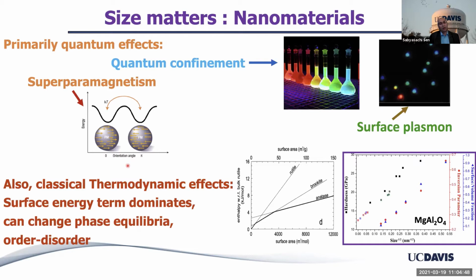But besides these quantum effects, there are also classical thermodynamic effects, which primarily come from the fact that the surface to volume ratio increases a lot when you go to tiny size. It's mostly surface. If you consider a tiny particle, almost 90% of the atoms could be near the surface. So in that sense, the surface energy term dominates and can actually change phase equilibria and change properties of materials. Here are a couple of examples. One is one of Professor Alex Navrotsky's work, who I believe is currently at ASU, when her group from UC Davis did this work. This is the phase equilibria of TiO2 nanoparticles in rutile, brookite, anatase, these polymorphs. They change their relative stabilities as a function of size.